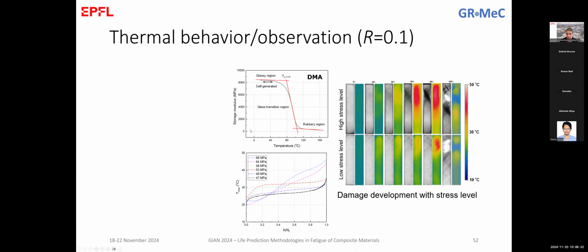Here is the thermal behavior. If you remember, we used photography with a backlight. These are the gray photos that you see here, and we also use the thermal camera that gives directly a measure of the surface temperature of the specimen. And you see that these two are correlated well. The damage that we can observe in the specimen is when the specimen becomes darker. These are cracks that are evolving in the specimen bulk. At the same time, at the location of this concentrated damage, we have an increase of temperature, which is the result of the increased friction in this location. And of course, at the end, when we go to failure, the temperature goes quite high.